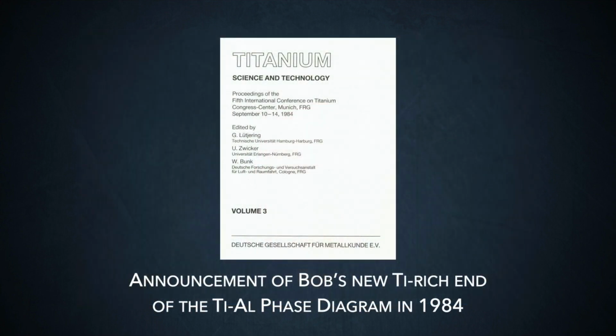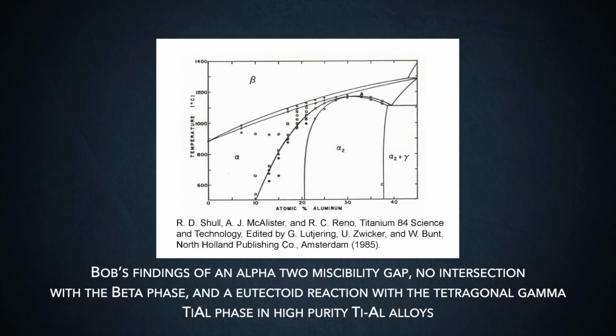And indeed, what we found is that the miscibility gap between these two hexagonal phases, alpha and alpha 2, at low temperature, came together at a high temperature to a single point, and that single point was not at a high enough temperature that it reached the alpha beta two-phase field. And so there basically is a miscibility gap rather than an intersection forming a paratectoid reaction with the beta phase, as most of the diagrams show.